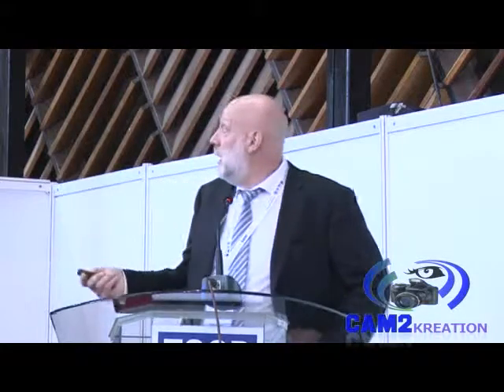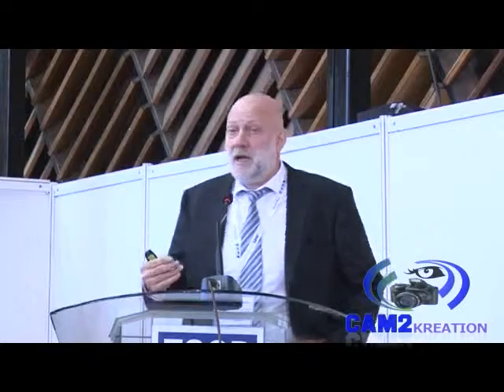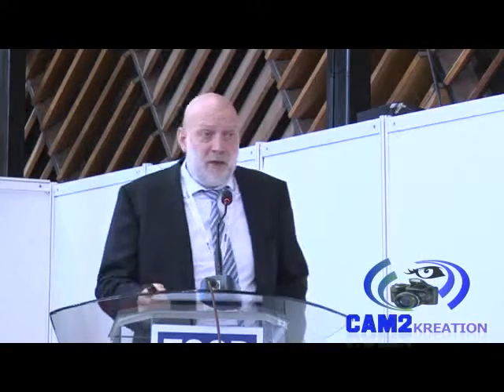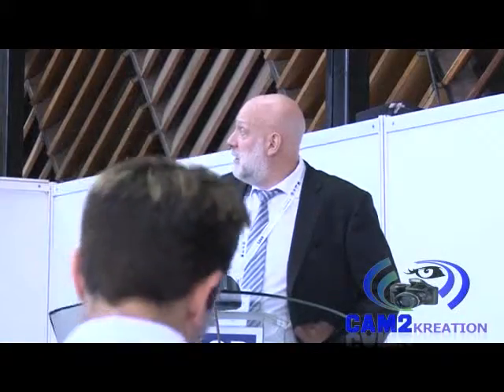Now let me come to the structure and processing. In your equipment, if you have a multi-layer equipment, you will put polyolefins. Polyolefins are usually the carrier of a structure, and at the same moment, they give you a perfect moisture barrier for the products. On the other hand, you have barrier materials like EVOH, like polyamide. This is the red one. And in the middle, you have a tie layer, you have an Admer. This Admer has a physical bonding to the polyolefins and a chemical bonding to the barrier material.